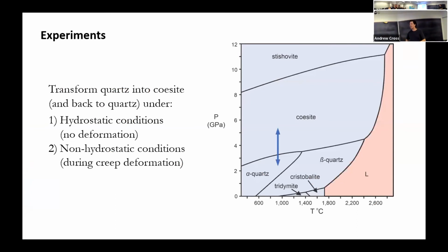All right, let's look at some experiments. So we've got our phase diagram for SiO2, pressure versus temperature. We're going to take a sample of hot pressed quartz. We're going to hold it in the alpha quartz field for some period of time. And then we're going to increase pressure under constant temperature, up into the Coesite stability field, hold it there for some period of time, and then bring it back down into the alpha quartz field.